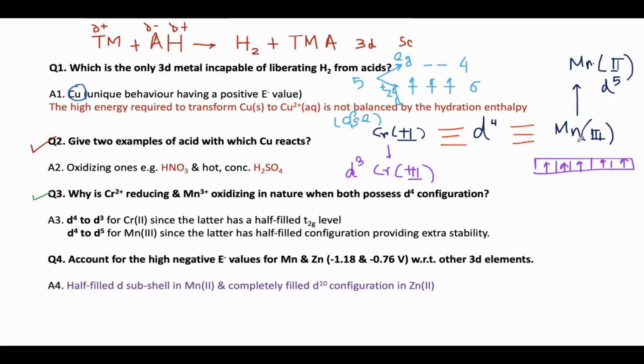But in the case of manganese 3, when it was d4, it actually takes up another electron. You can see here why it is the anomaly. You see the manganese 3 and this chromium 2. The charge density of manganese 3 is much higher than that of chromium 2, because we are going from left to right in the series. So from titanium, we are going to zinc. So chromium is here. On the right hand side of chromium, it is manganese.